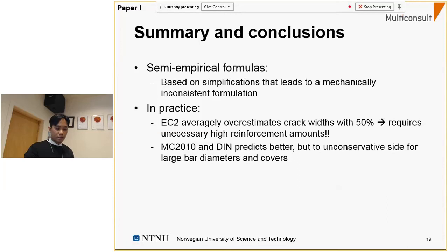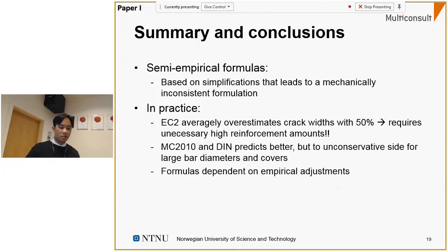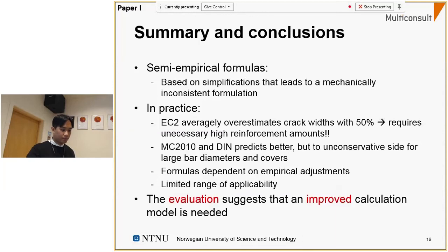The Model Code 2010 and the German annex predict the crack widths better, but on the unconservative side for large bar diameters and covers, and are thus inconsistent in that formulation. The formulas are very much dependent on empirical adjustments, meaning that there's a limited range of applicability of the formulas, and care should be taken when used in design of large-scale concrete structures.